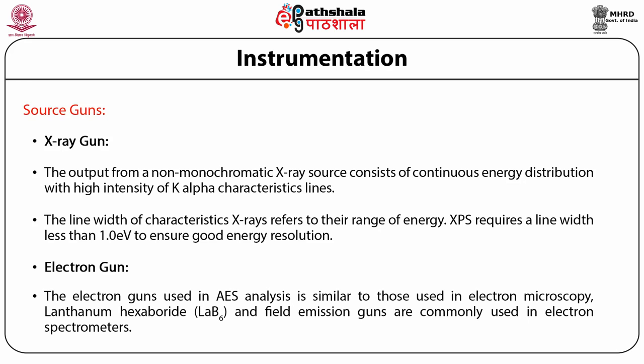The electron gun used in AES analysis is similar to those used in electron microscopy. Lanthanum hexaboride, termed as LaB6, and field emission guns are commonly used in electron spectrometers. Lanthanum hexaboride provides an electron beam of high brightness with spatial resolution of 200 nanometer. Field emission guns provide superior brightness and higher spatial resolution than lanthanum hexaboride, and also their emitting surface remains clean during operation without adsorption of gas molecules.